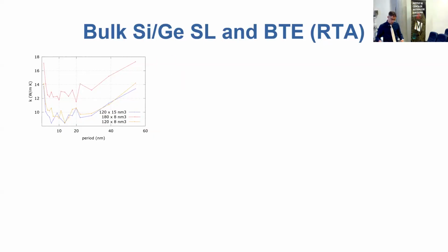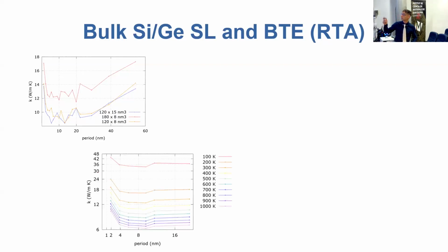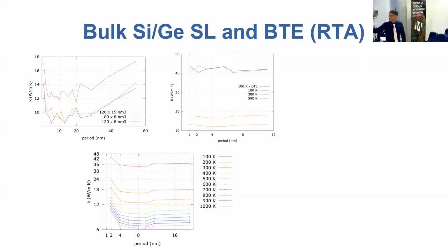And then we adopted a slightly more sophisticated technique to simulate thermal transport across the silicon germanium superlattice, which does not rely on a phenomenological potential, but rather on quantities that can be derived directly from quantum mechanics. This goes under the name of BTE, the Boltzmann transport equation. Basically, you can imagine that it's just a transport equation for the phonons inside the superlattice, and we chose also a specific approximation. And we computed the thermal conductivity of the bulk silicon germanium superlattice at different temperatures and for different superlattice periods along the two different crystal directions, in particular 111 and 100.